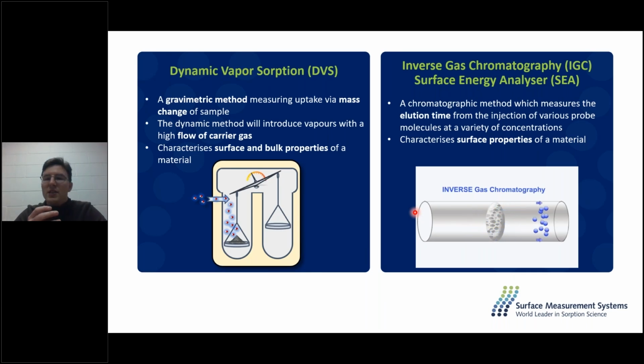So on this slide, you can really see the major differences between the two most popular techniques that we manufacture at Surface Measurement Systems. So on the left, we've spoken lots today about how this is a gravimetric method, how we're observing mass change as a function of carrier gas versus probe introduction with a carrier gas, or just probe introduction with a vacuum. Now, the IGC SEA stands for Inverse Gas Chromatography Surface Energy Analyzer. So it is an instrument that has been designed to optimize inverse gas chromatography experiments. And one of the main applications of this instrument is to measure the surface energy of our samples.